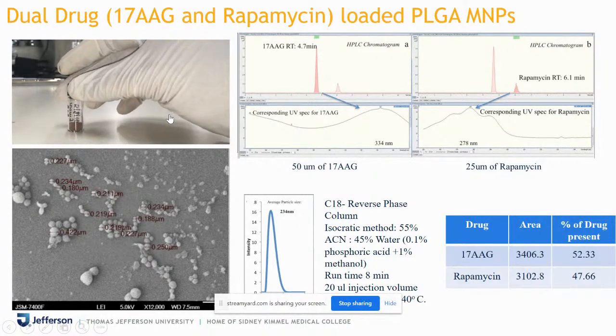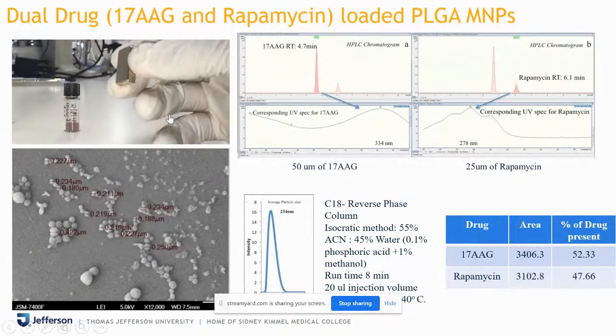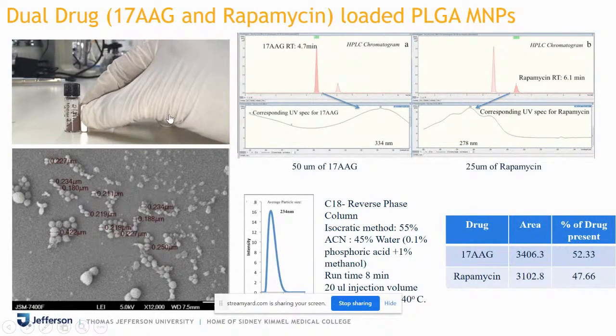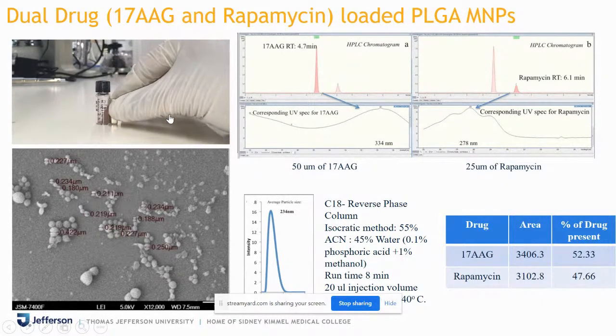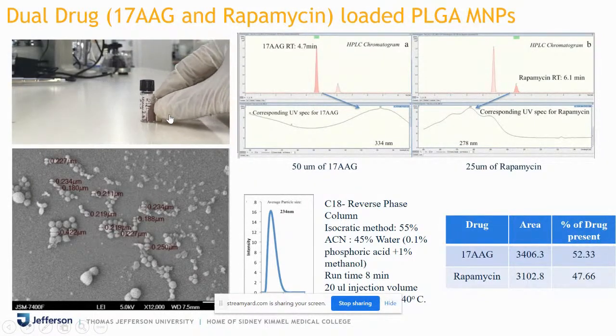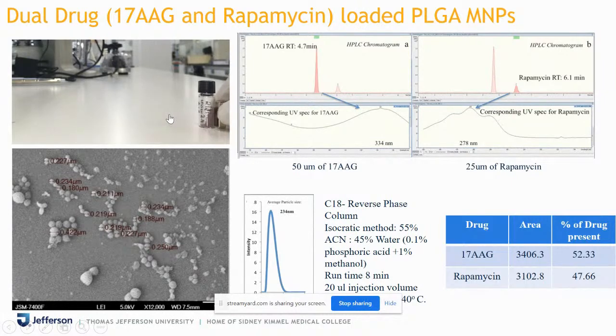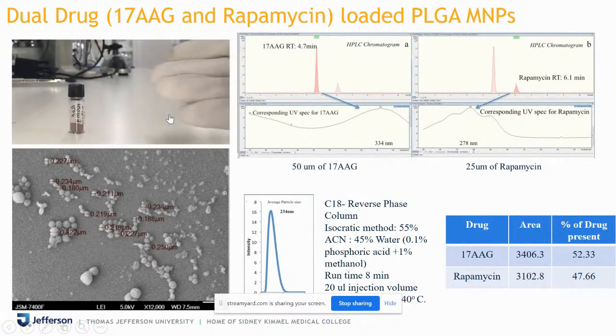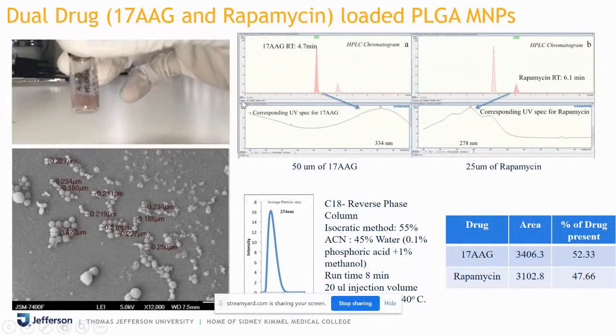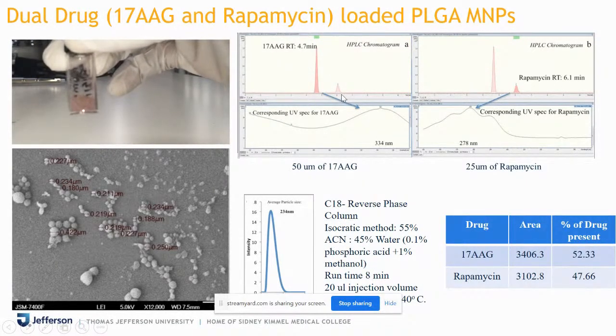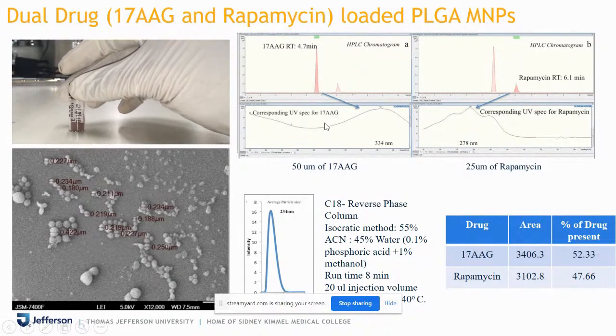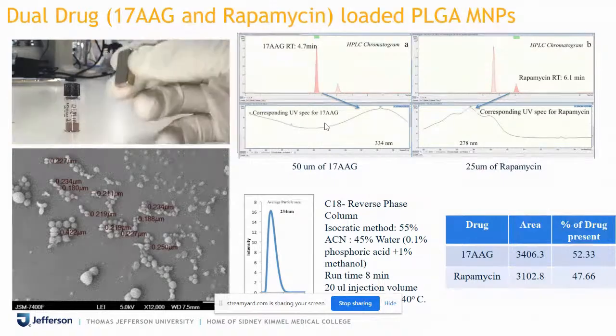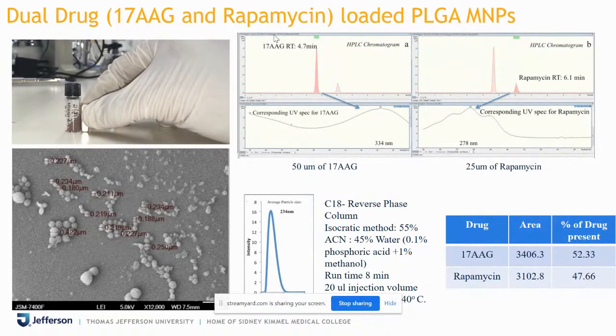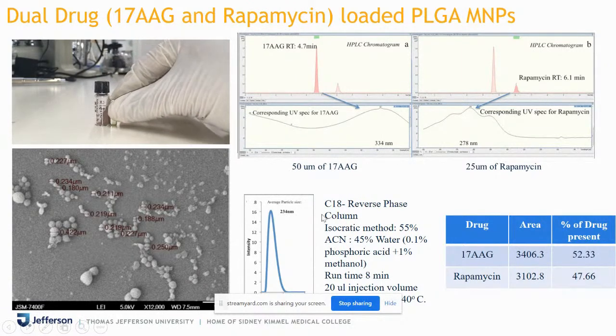When you expose it to the magnetic field, the particles are so strong that with a normal magnet you can just drag the entire vial. And this is currently under development for further cytotoxic evaluations. This drug, 17-AAG, was co-encapsulated with rapamycin in this system. The screen shows the HPLC method used for simultaneous estimation of 17-AAG and rapamycin in a single method. The retention time for 17-AAG was 4.7 minutes, and for rapamycin it was 6.1 minutes.